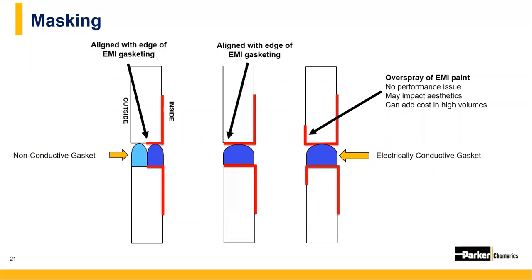Yeah, I wanted to mention that complex parts can require fixtures to be created for ease of masking the parts. And actually, more importantly, the masking tape that's used should be checked to be compatible with the solvents in the paint. So if the tape is not compatible with the solvents, those solvents can actually eat away or soften the tape and the adhesive on the masking. This can create a pretty big mess and actually limit the clean lines that the masking would typically add.